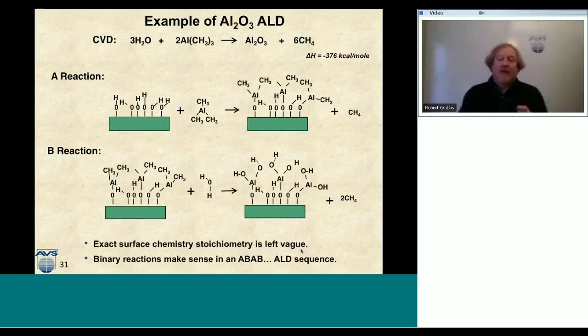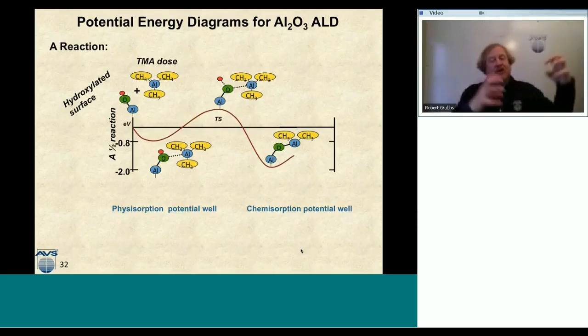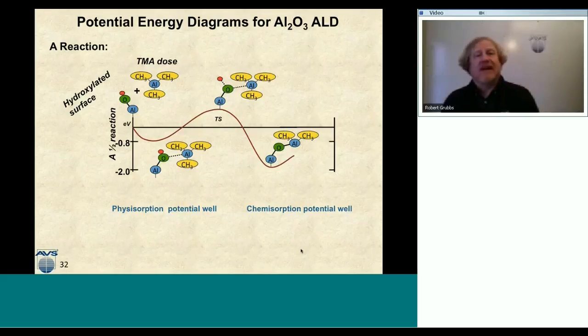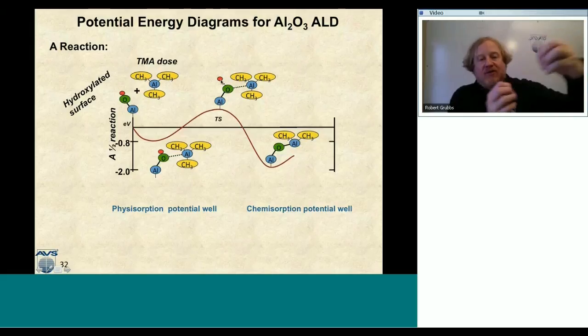So now let's take a quick look at the aluminum oxide ALD reaction in a little more detail in terms of the physical chemistry of it. So here's the potential energy diagram for the aluminum oxide reaction. And I start with this hydroxylated surface, and I come down with this dose of trimethyl aluminum. And notice that we fall into this slight physisorption well right here with the aluminum making a slight interaction with probably the non-bonding electron pair of that OH on the surface. This is this physisorption well. And then as I start to move up the potential energy diagram to the transition state, I'm sort of quasi-bound. I make an aluminum-oxygen bond that's kind of happening, but that oxygen-hydrogen bond is also getting weaker.